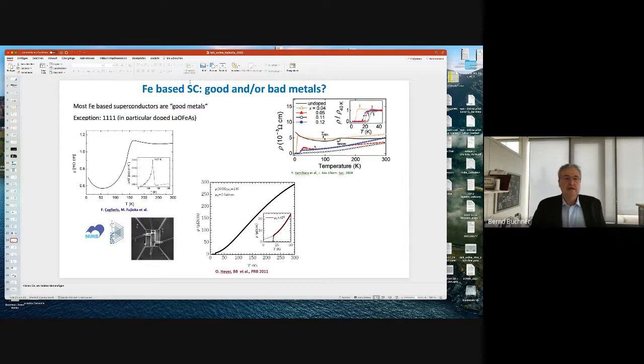And this brings me to another point, which I have to address now. So these 1111 type compounds, so these lanthanum, oxygen, iron, arsenide, are somehow peculiar materials, not only from materials point of view, they are also from the electronic properties very different. So if you plot the resistivity, and this is the smallest resistivity which I think has ever been measured on single crystals on these systems, you see a lousy metallic state, and you see even an increase here when cooling down. And then this phase transition comes, first the structural one and then the magnetic one, and then the strong decrease. The fact that we see the strong decrease means that this increase here is intrinsic. So we are really dealing with a bad metal. We are very close to localization in these systems.